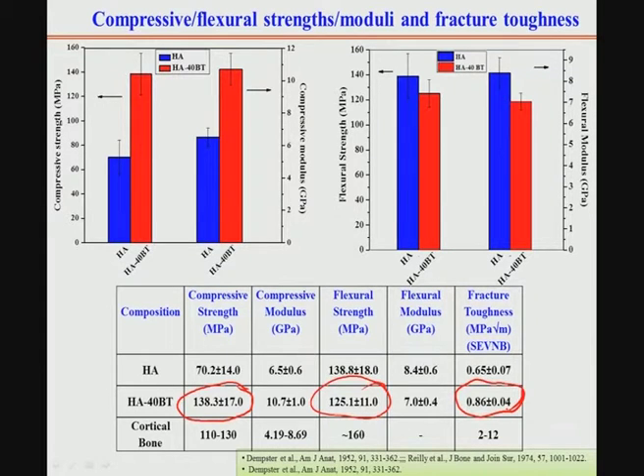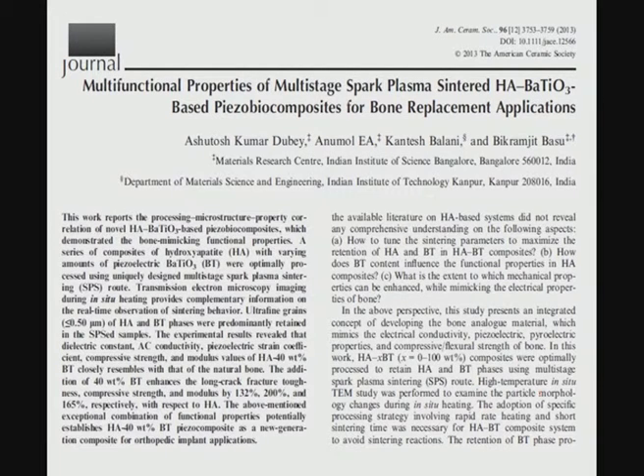In an earlier module, I mentioned that fracture toughness of hydroxyapatite composite can be significantly enhanced to close to 5 MPa square root meter when one adds 10% of titanium. So, with such a small volume percent of titanium addition, fracture toughness can go almost 5 times higher than what we have achieved here in the hydroxyapatite barium titanate composite. So, physical property wise, certainly this material is not at a very high level, but what we see here is that this kind of compressive and flexural strength combination is moderately higher than even other materials, not only hydroxyapatite titanium.